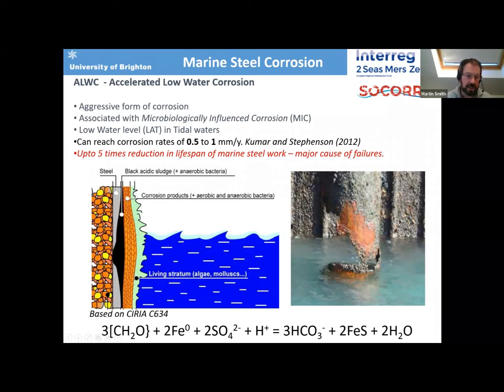And for anyone who's ever looked at microbial diagenesis, this generalized equation for what's happening is fairly familiar. We get bacteria that reduce sulfate from the water column under anaerobic conditions. They produce hydrogen sulfide, and they're using that to metabolize organic matter. The reduced hydrogen sulfide reacts with iron and generates mackinawite or pyrite. So that core process is happening on the steel surface in the marine environment. And we get really dramatic failures.